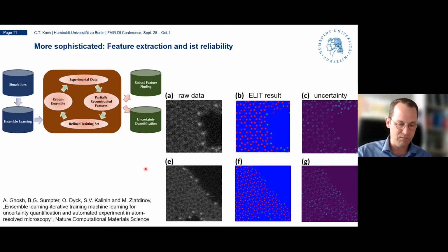So this is a tool developed by the group of Sergei Kalinin at Oak Ridge National Lab. And instead of only extracting atom positions, they also extract the reliability of these atom positions. So if you have enough data, you can run different reconstructions with different seeds and different parameters, and then also get some information about the reliability of a reconstruction, something that, for example, we wouldn't have. But once these algorithms are shared on a common database with a common data format that processes our data very easily, then we can immediately also gain information of this type. So there's a lot of benefit in sharing these algorithms and also the data.